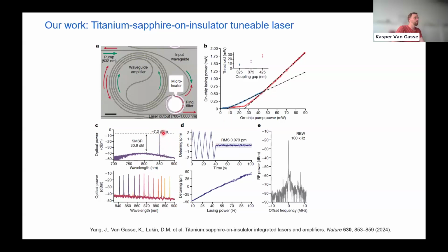It can be single mode. We get pretty good stability. We can lock it using just this microheater. Instantaneous line widths on the order of 100 kilohertz. So a very high performance laser.